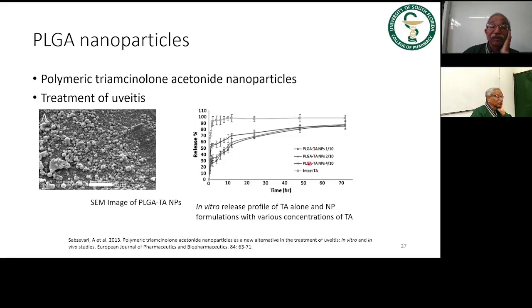You can use different types of polymers and you will get, this is the typical, if you inject the drug directly, and then if you inject in polymeric, you will see that the sustained release is much longer, many days, hours, 70 hours it can be retained there. So this is a scanning electron microscope image of the PLGA triamcinolone acetonide nanoparticle. This is how they look like, and in vitro release is there.